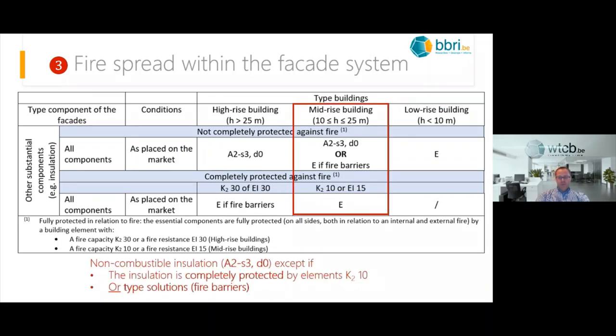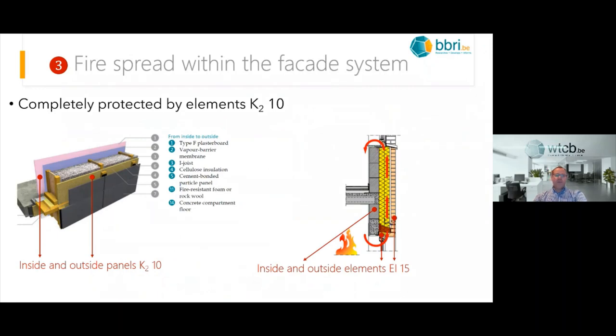For mid-rise buildings, so buildings between 10 and 25 meters of height, the essential components, such as the insulation, must have a fire reaction class A2-s3,d0. But if the insulation is completely protected by elements with a K2 10 or EI 15, the insulation may have a fire reaction class E or better. So you can also use type solutions by installing fire barriers, and I will come immediately to that. First, completely protected by elements K2 10, or for high buildings it's K2 30.